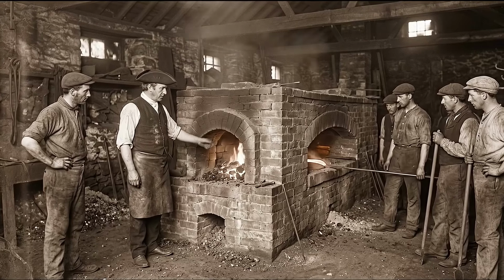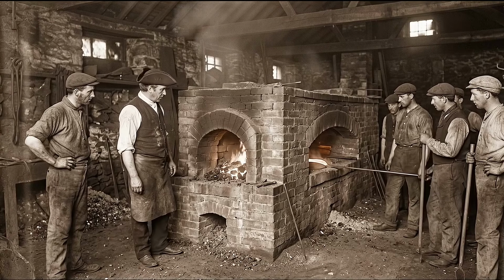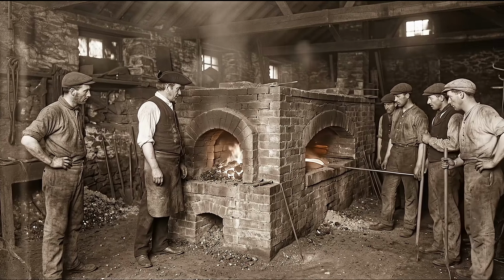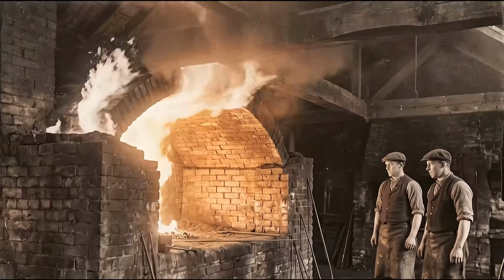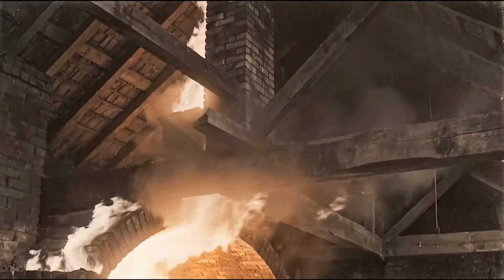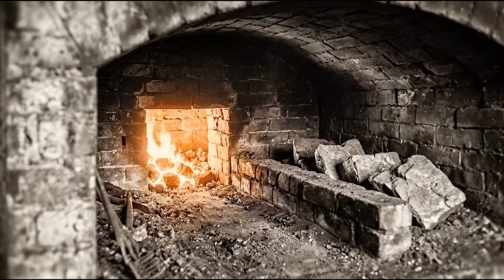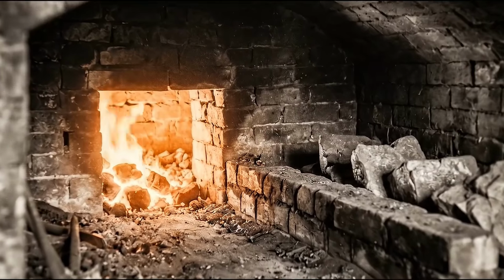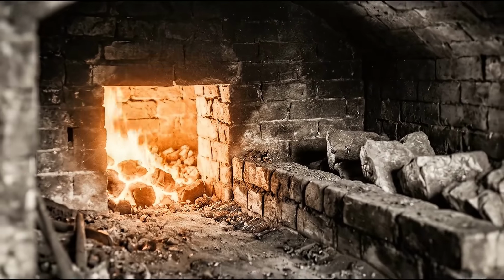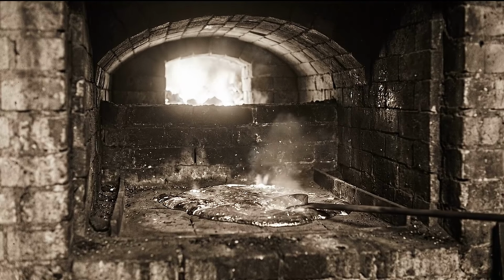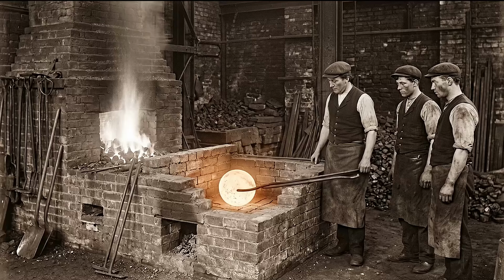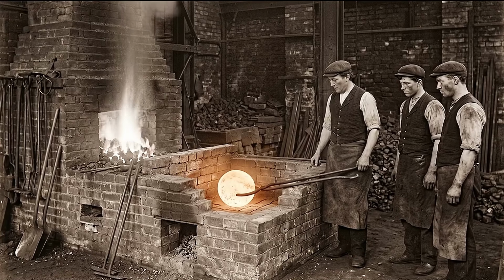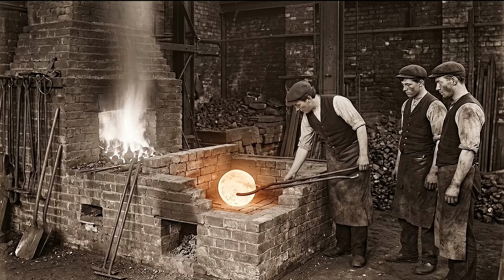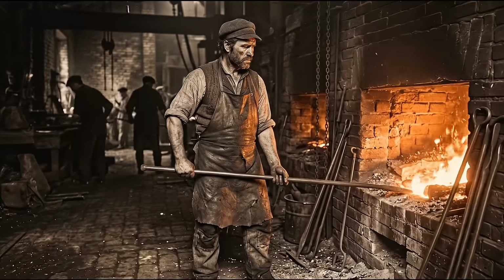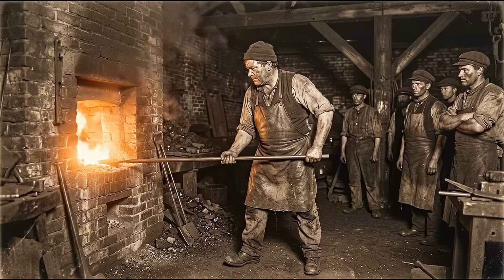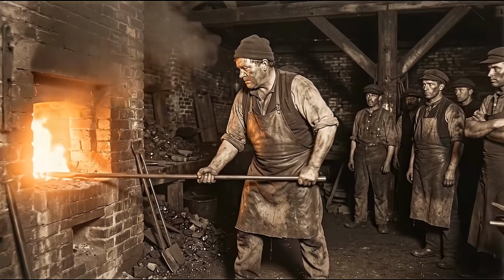Cort solved it by keeping the coal separate. In his furnace, the coal burned in a firebox at one end. The flames and hot gases rose up, swept across the arched ceiling of the furnace, and radiated down onto a shallow hearth where the pig iron sat on the other side of a low dividing wall. The metal melted from reflected heat, never touching the fuel. That separation meant you could burn coal all day and the sulfur stayed on its side of the wall. But melting the iron was only step one. The carbon still had to come out, and that is where the real work started.